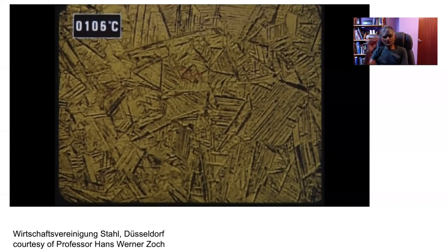Now, these shape deformations are quite large. And if they are elastically accommodated, that means the strains that are caused in the surroundings are purely elastic, then the interface between the austenite and martensite is reversible. But if the strains cause plasticity in the adjacent austenite, introduce defects and so on, then obviously a glissile interface will tend to be retarded by those dislocations or even pinned by any hindrances in its path. And therefore reversibility becomes impossible without excessive heating.